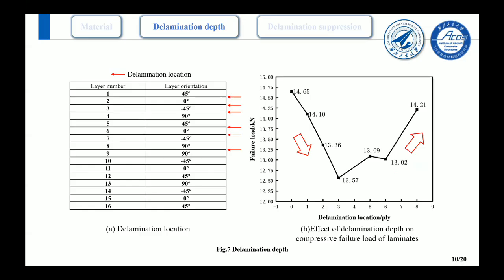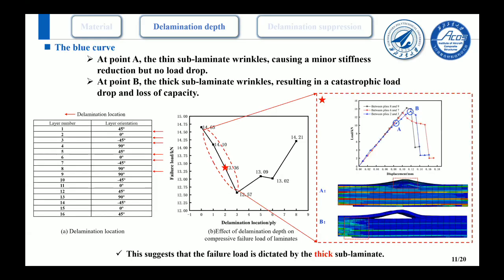Based on the established finite element model, in the depth direction, the position of the delamination was varied. The computational results presented in Figure 7b indicate that the compressive failure load of the composite laminate exhibits a trend of initial decrease followed by an increase as the delamination depth progresses. Finite element simulation provides the explanation for this trend.